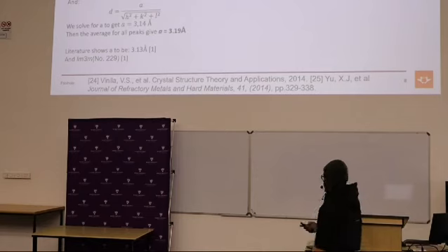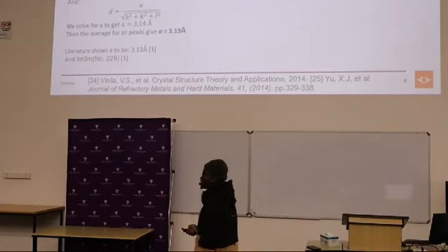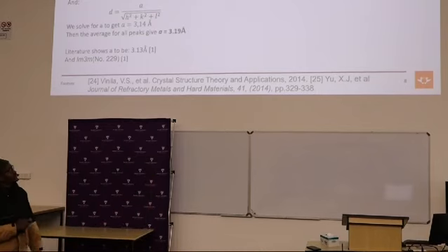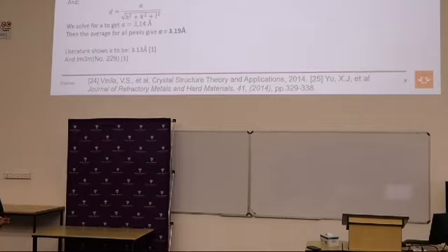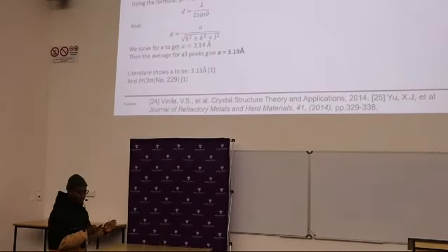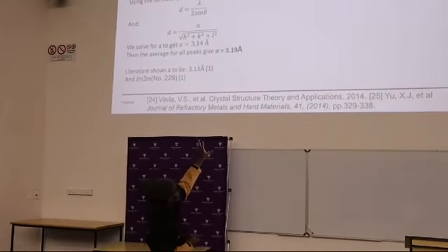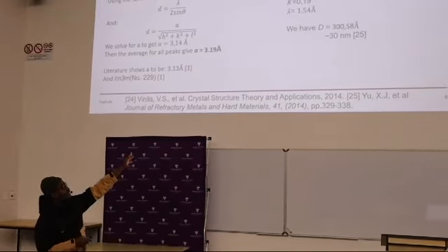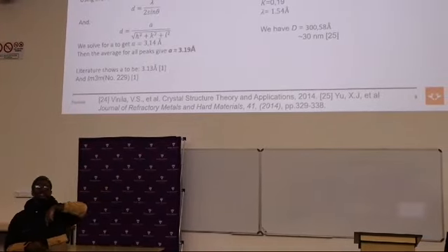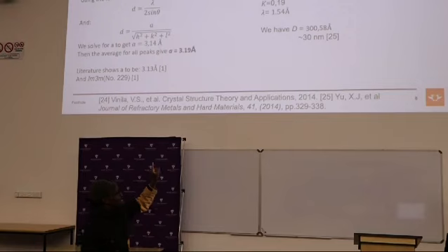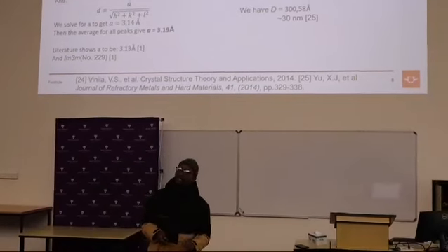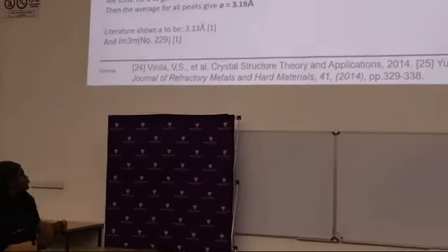Now, we also went on to find, of course, the crystallite size, as I said, and the method that we used, we applied the Scherrer equation. There may be issues related to this equation, but of course, for the purpose of demonstration, in terms of the crystallite size, we used this to characterize, and from this, we found that the value was about 300.58 angstrom, which if one converts to nanometers, is about 30 nanometers, and that also is in agreement with already studied literature on this material. And of course, I provided again the references for some of those.